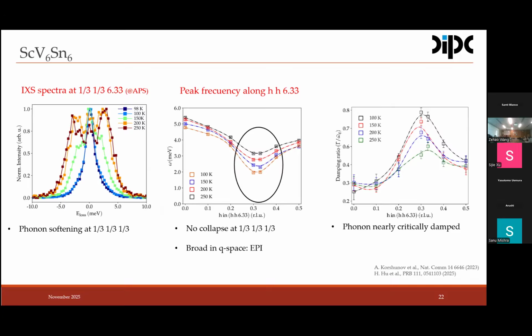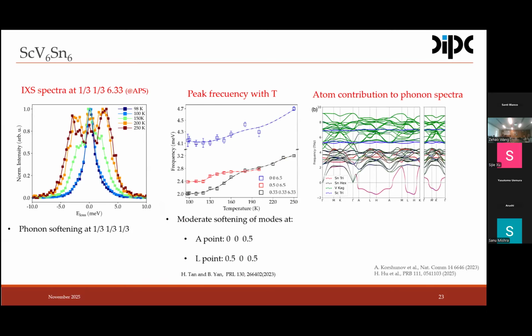But in any case, if we track the temperature and momentum dependence of the line width, it tells us about the lifetime of this mode. It actually goes to an overdamped critical regime. If we measure the temperature dependence, not only of the phonons related with the charge order, with the propagation vector of the precursor of the charge density wave, but of the phonons at the high symmetry points like A and L, we clearly see how all the phonons soften with temperature. So essentially what we are dealing with here is not a soft mode.